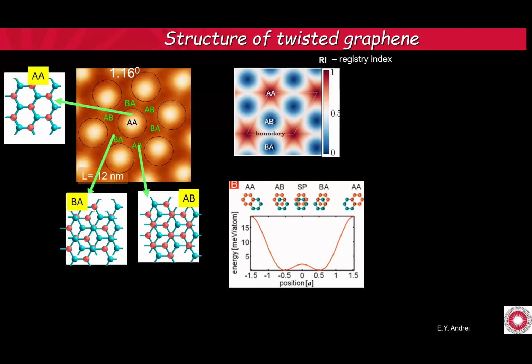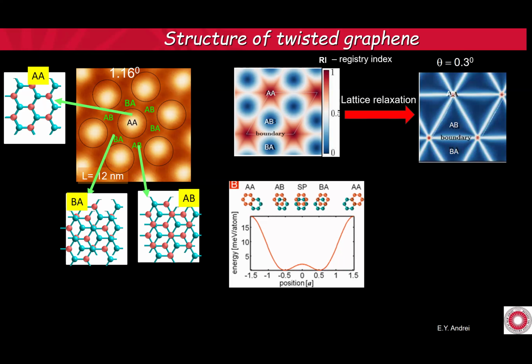But in fact, if you look at the energetics of stacking, you see that AA stacking is extremely expensive. It costs about 20 millielectronvolts per atom to have AA stacking. So the lowest energy stackings are AB and BA, and we have a saddle point in between that's a little bit higher. So of course, if the system can, it will reorganize, it will adjust to minimize its energy. It's going to pay strain energy in order to gain van der Waals energy. And you see that if you take this into account, when you go to 0.3 degrees, where you have a huge Moire cell, the AA regions shrink to a tiny percent of the area. Of course, they can't go away, they're like vortices, but they shrink a lot.